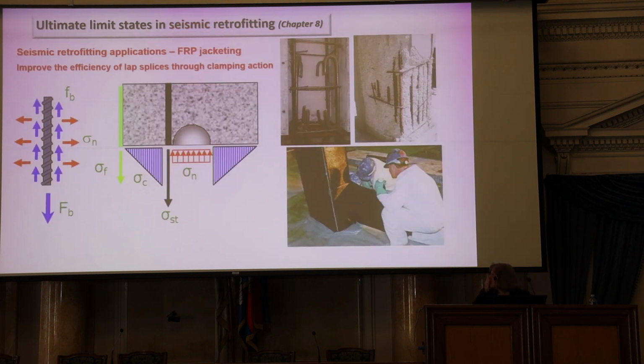Another thing that works with FRP is clamping of lap splices. So you have two bars lapped, usually at the base of a structural member in old construction. If this is not clamped by transverse reinforcement, it's going to slip and you're not going to ever be able to develop the strength of your reinforcement. FRP jackets help that, because as the bars slip against each other, they dilate, they try to create space in order to slip because they are ribbed. And that slippage engages the transverse jacket.